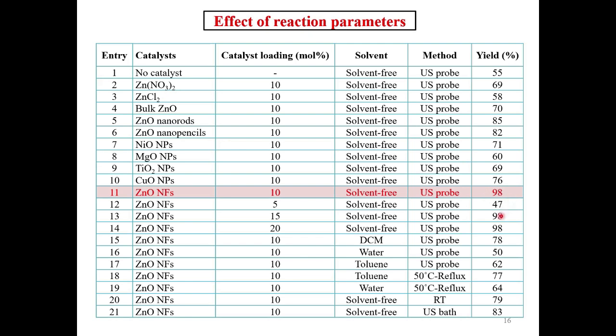In this case we have 98%, but the amount required of the catalyst is 15 mole percent and 20 mole percent. If we get 98% at 10 mole percent, then why should we go for the extra 5 and 10 mole percent of the catalyst? Then if the reaction is satisfied up to 10 mole percent, we have concluded here that zinc oxide nanoflowers loading of 10 mole percent is sufficient, and so under solvent-free condition in presence of ultrasonic probe, it gives 98%. Therefore very satisfying results are obtained at this particular juncture, and we recommend that 10 mole percent is sufficient for the zinc oxide nanoflowers.